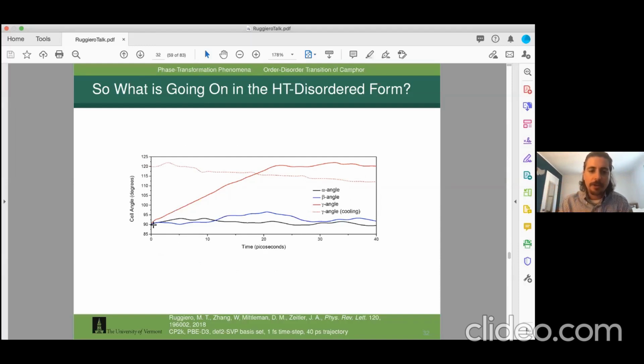We started with an orthorhombic cell, 90, 90, 90 degrees, then watched what the unit cell did. Two of the angles stay around 90 degrees, oscillating a little but staying right around there, while one of the angles makes a straight shot for 120 degrees and then stays there.